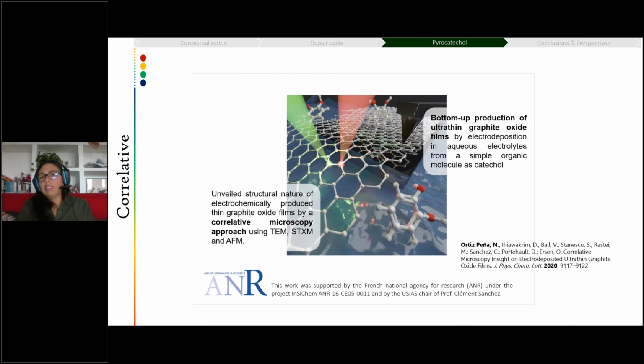So in this study, we finally showed that we are able to produce graphite oxide in really mild conditions from a simple organic molecule, which is a very good thing, but more so that we could use this system to do correlative approaches. For example, in this case, using TEM, STXM, and AFM to create a more complete picture of what is happening in our reaction.